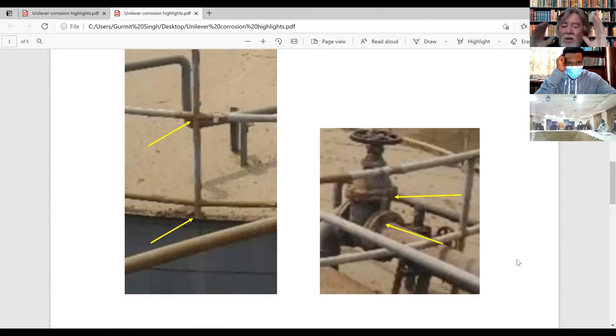On any bolted joint on any structure, when you bolt two pieces of metal together, they call that a man-made crevice. And of course, crevice corrosion is one of the biggest corrosions in the world after general corrosion, because whether it's vertical or on its side, when you get rain, sea spray, overnight condensation, the water will sit on the outside of that joint. And because you have a crack, you have capillary action, and inside the crack there's a lower pressure, and it starts sucking in the water. And when it sucks in the water, it sucks in the salt. So you have very bad corrosion inside there.